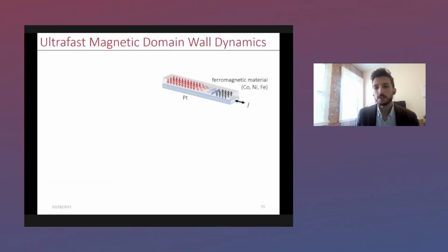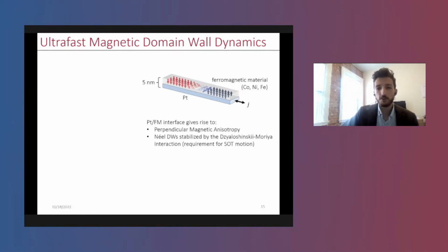So the canonical system that's used predominantly today to study domain wall dynamics is an all-metallic system. It's based essentially on elemental magnetic systems, where you essentially have a thin bilayer of platinum or some other heavy metal coupled to a ferromagnet that's once again usually elemental in nature. And so this structure is actually quite useful. It gives rise to many effects such as PMA, which is needed for scalability, and also stabilizes the correct type of domain wall that's needed to drive motion in domain walls. It stabilizes an Néel type from the Dzyaloshinskii-Moriya interaction.